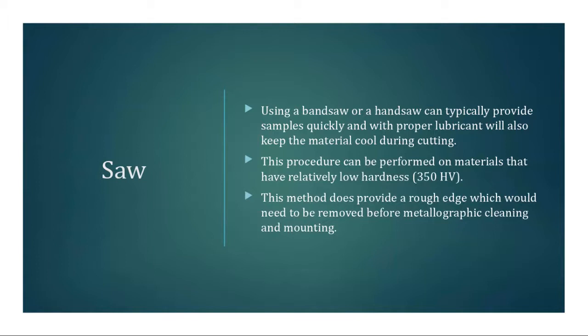And I typically use the bandsaw on materials that have low hardness. The reason why is because the blade that I have on the bandsaw, I do not want to go and spend a lot of money on very expensive blades for one-time use. I would rather do that on the abrasive lubricant-cooled wheel. So I typically cut softer materials on the bandsaw, and the only downfall is, yes, you get a clean cut, but you still have a lot of mechanical damage on that edge, and that will definitely need to be ground through enough during the metallographic process.